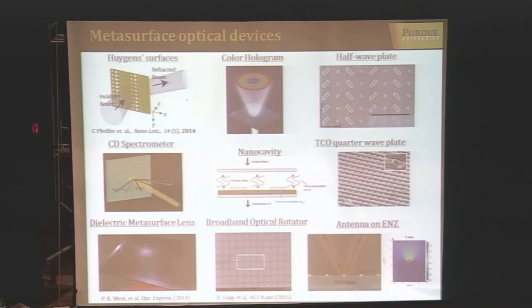You could make a cavity much smaller than the wavelength, because the way a cavity works, after one round trip you have to restore the phase front. Normally it takes a size comparable to the wavelength, but if you shift the phase using this antenna, it could be much smaller than that.